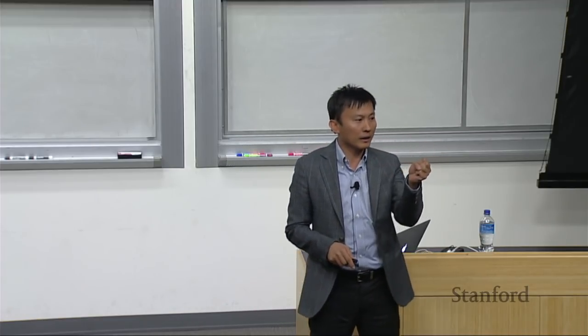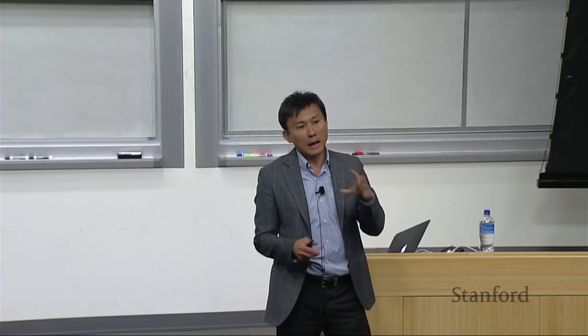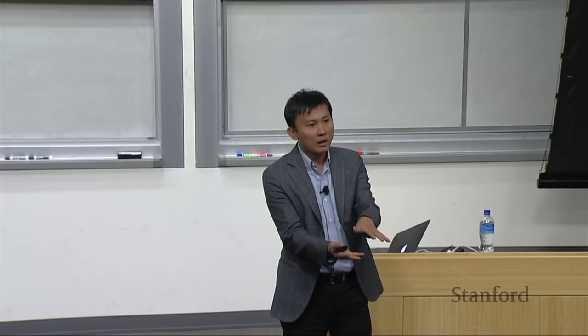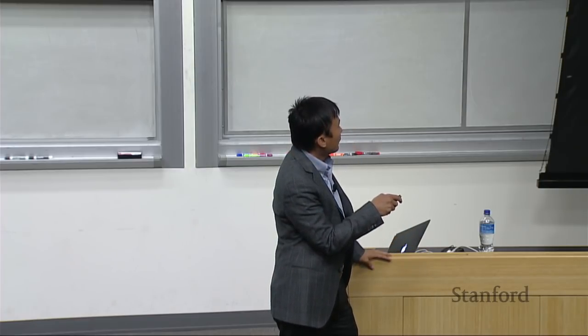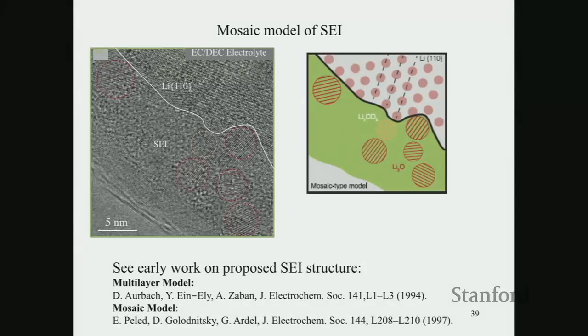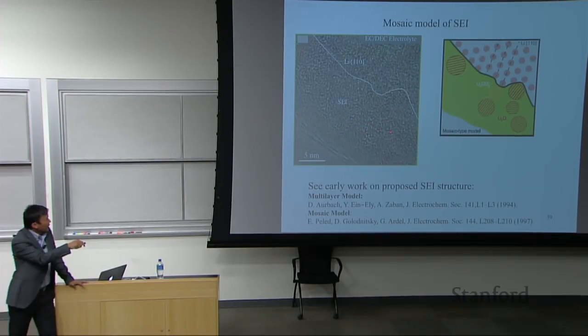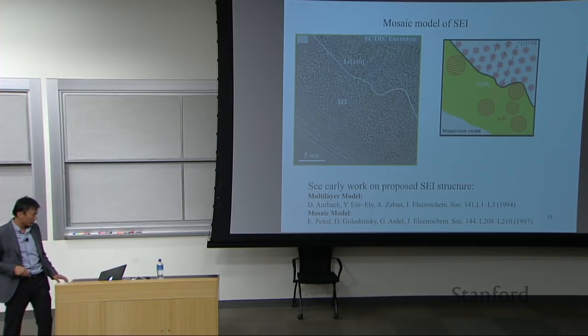Mosaic model means in this interfacial layer, you have inorganic nanoparticles of decomposition compounds embedded into an organic matrix of polymer. So indeed, under this so-called EC/DEC electrolyte, we can identify, this is a schematic drawing of a nanoparticle of lithium oxide, lithium carbonate, embedded into this green color amorphous matrix of polymer, decomposed and formed by this electrolyte. We can identify, if you could see this image clearly, a projection on the screen, atomic scale resolution, these inorganic particles in the organic matrix.